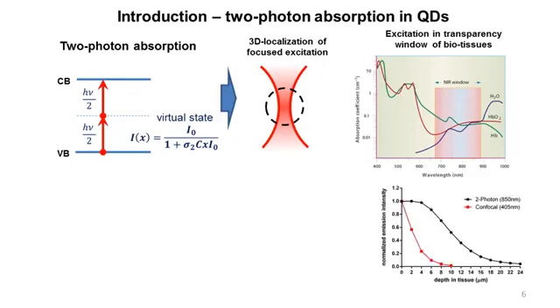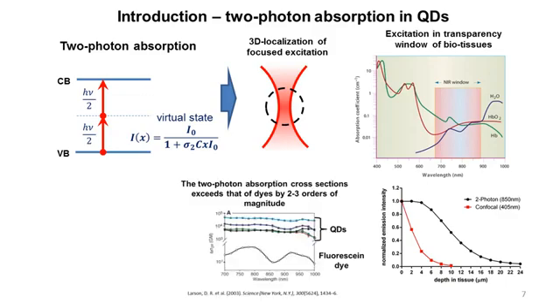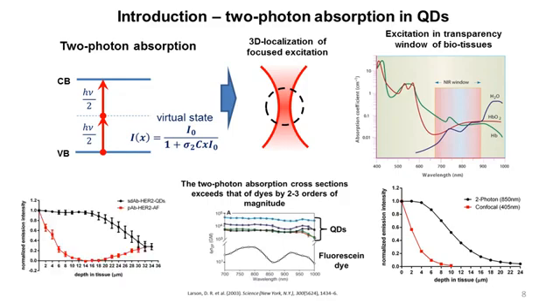The use of excitation in the spectral range of these windows allows radiation to penetrate into biological tissues deeper than the other spectral ranges. For this application, quantum dots are significantly better than traditional organic dyes due to the uniquely large two-photon absorption cross-sections of quantum dots. This allows us to increase the depth of the detection inside biological tissues further.